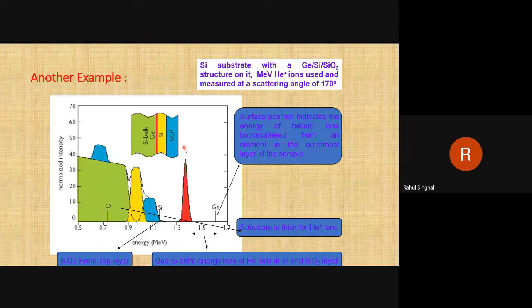Yes, sir. So the silicon which is present on the surface, we are getting this peak. But one silicon is present in the substrate also, within the depth, so this peak should come at much lesser energy. This other peak is due to the silicon which is present in the depth, this bigger one. It's not a peak, it's like a hump. So this hump is due to the silicon present here. Now one silicon is present here also, so we are getting this kind of peak. In that way we can get an elemental idea of which elements are present and at what depth they are present.